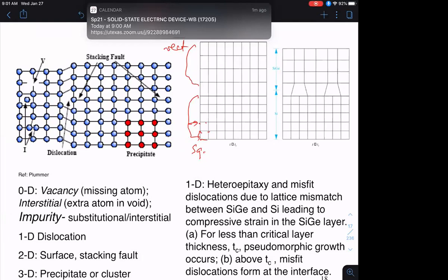Then at these lattice points, so far it's just a mathematical array of points where the symmetry determines the lattice type, okay? So in the case of a square, for example, what type of symmetries am I talking about? Well, clearly, if you rotate the lattice by 90 degrees, you go back to the original lattice, 180, 270, 360. So those are examples of rotational symmetry. Or you could take a plane like so and use that as a mirror to reflect the left-hand side onto the right-hand side and vice versa. So that's an example of reflection symmetry, and so on and so forth. And all of these, although we won't get deeply into those, if you take a graduate course, you'll see have very, very important implications for semiconductor devices.